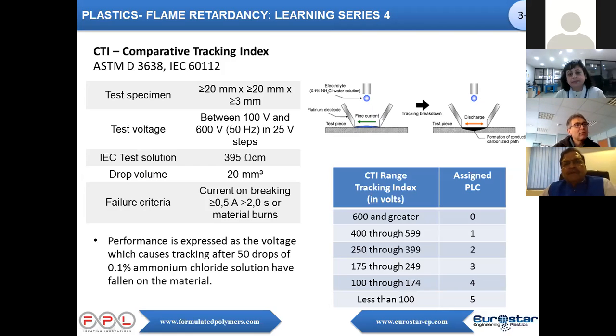Then these droplets fall between those two electrodes every 30 seconds. So every 30 seconds you have a drop going down, and of course there is a current applied to these electrodes. The pollution tends to make contamination on the surface, and if the current is high enough, there is a formation of a conductive carbon path between the electrodes, up to a standardized level of current. If a standard level of current is reached, then the measure is done.